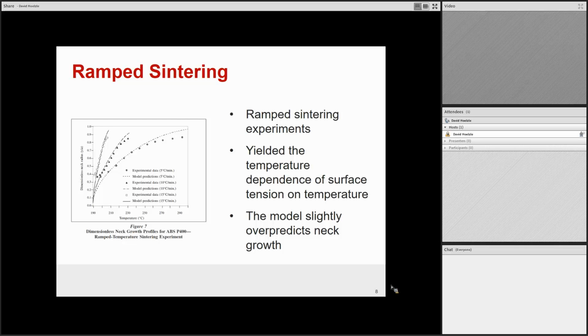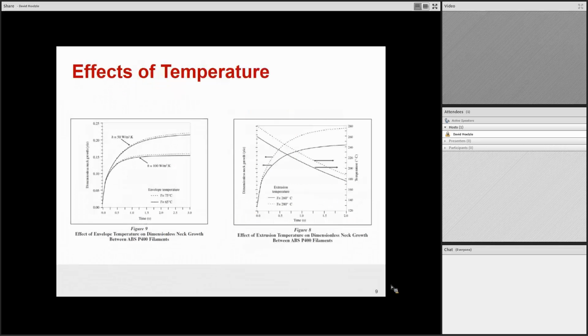They were able to actually determine that as the filaments get hotter, there's a negative correlation to the surface tension. So as the filament got hotter, there was a negative value for each degree Celsius that you're going up, meaning the surface tension is going to decrease. So they conclude that there's potentially an optimum that you could reach in terms of extrusion temperature. These two graphs are different effects of temperatures that you have control over when you're doing an additive manufacturing process with material extrusion, specifically ABS plastic.